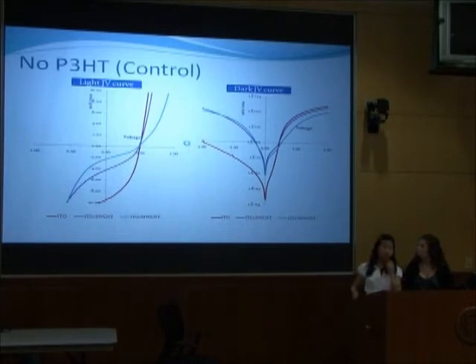The graphs you see here are for our control small molecule cell. This has no hole transport layer. As you can see, we see shorting in the devices with nanotube anodes. This is because the nanotubes are sticking out of the transport layer and contacting both the anode and the cathode and creating a short circuit.